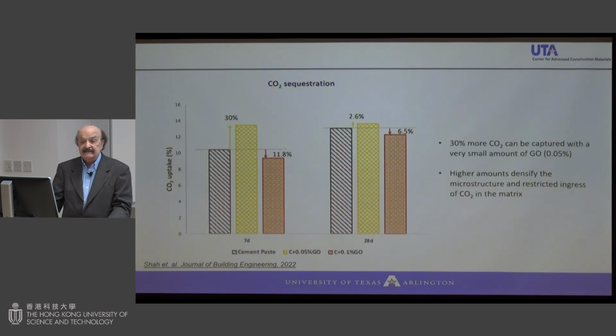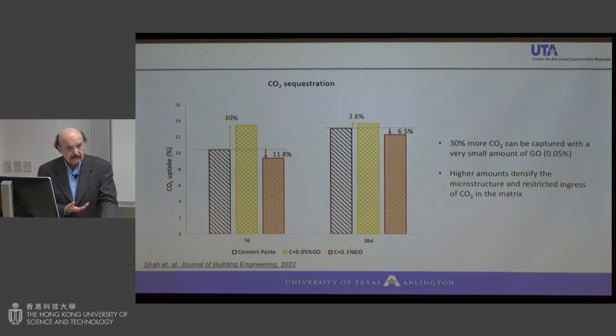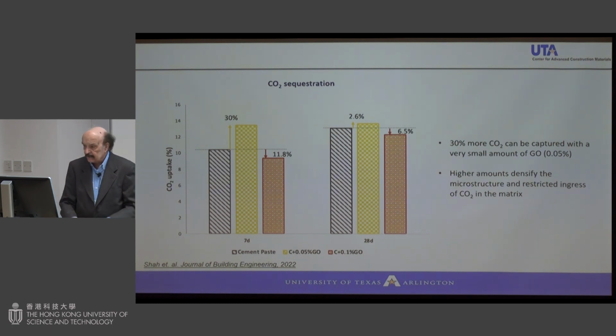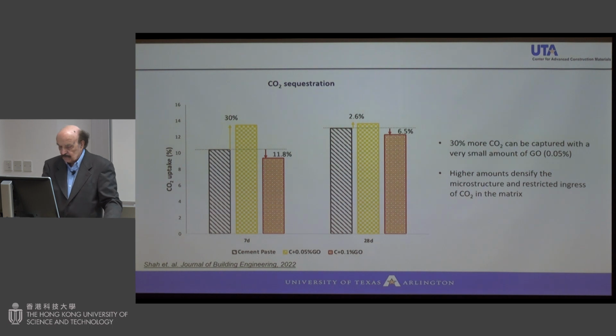So look at the CO2 uptake, just concentrate on that. The CO2 uptake of cement paste, when we have 0.05%, you increase CO2 uptake by 30%. That's really substantial, and you have other benefits that we have talked about of adding graphene-based materials. And I will talk about a few other additions later on. So I think that this is very interesting work, and as far as I know, it's the first time we showed that addition of graphene-based material can increase CO2 uptake.